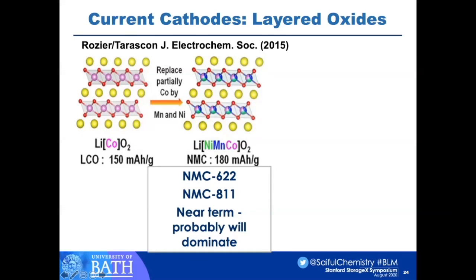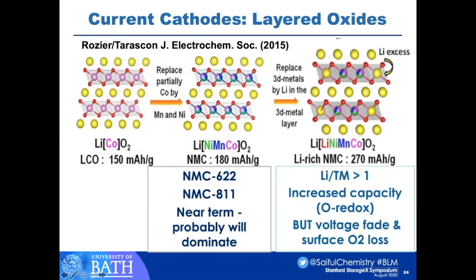But there's a lot of research looking at lithium-rich NMC and lithium-rich layered oxides. Lithium-rich here means that the lithium to transition metal ratio is greater than one. You increase the capacity by now enabling oxygen redox in the system. But there are significant challenges around voltage fade and surface oxygen loss. But the energy densities are higher, greater than 250 milliampere hours per gram.